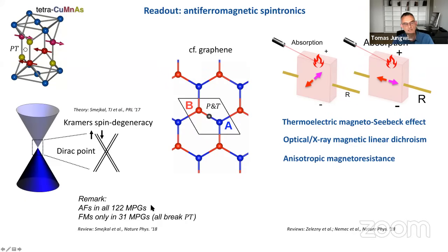Another side remark here is that if we look at all possible symmetry groups of magnets, there are 122, and all of them can host antiferromagnetic order, including those with the PT symmetry, while ferromagnets are only a subset of 31 of these magnetic point groups. So that already tells you that if you're looking for some special symmetry, and by symmetry allowed some special topology in the band structure, antiferromagnets will give you a much broader playground. But how can we use it for some magnetoelectric response?